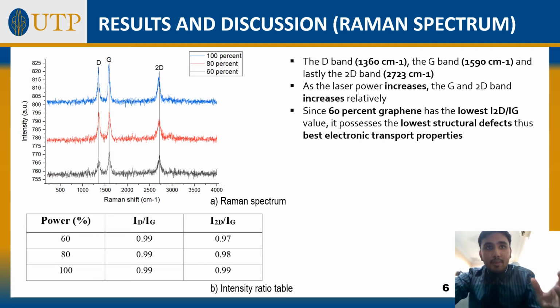To summarize this table, I would like to say about the D band over G band. Basically, this ratio remains constant, showing that the crystallinity of the graphene is not affected by laser irradiation. The 2D band over G band value increases but achieves a value less than unity, showing that samples are multi-layered graphene samples. Then, to summarize this table, 60% graphene has the lowest intensity ratio, thus it has the lowest structural defects, and plus it has the best electronic transport properties.